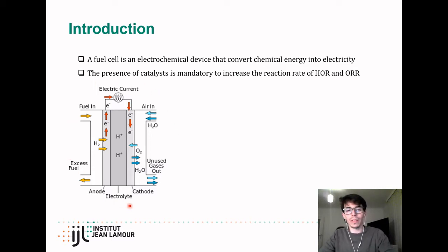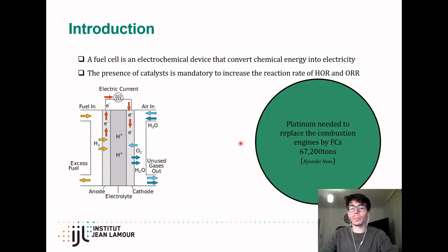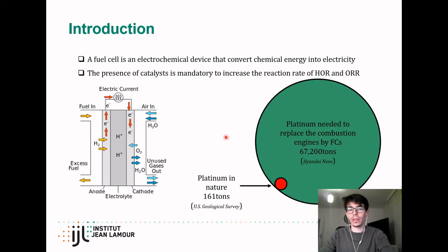However, the presence of electrocatalysts is necessary with the aim of increasing the kinetics of the hydrogen oxidation reaction in the anode electrode and the oxygen reduction reaction in the cathode electrode. One of the main limitations of this device is the use of platinum as electrocatalyst for both anode and cathode reactions, since, as we can see in the next illustration, the platinum needed to replace all the combustion engines by fuel cells is much bigger than the platinum we can find in nature.